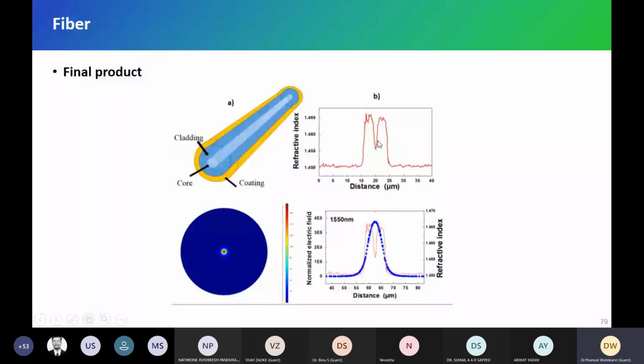We don't get this dip if we are using vapor axial deposition. In OVD, we also get a dip, even though there is no GeO formation. The reason is that in OVD, if you remember, we take the target rod, a graphite rod, over which we deposit, because we need something over which to deposit. Then we have to remove that target rod, and while removing it we damage it a little bit, so we get a central dip in OVD also. So OVD has a central dip, MCVD has a central dip, axial deposition has no central dip.